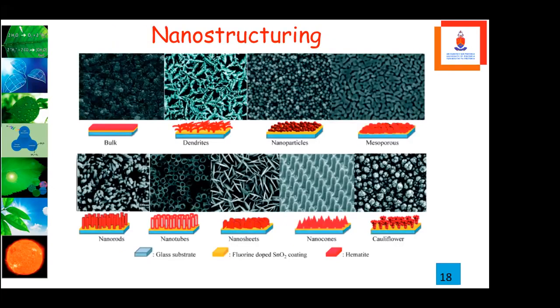These are the nanostructures that we have achieved in our labs: the dendrites, nanoparticles, mesoporous phases using dip coating, the cauliflowers, the nanocones, and all of this. Whilst we have achieved them in our lab, we don't claim that we are the first people to achieve that. Other people have achieved that.